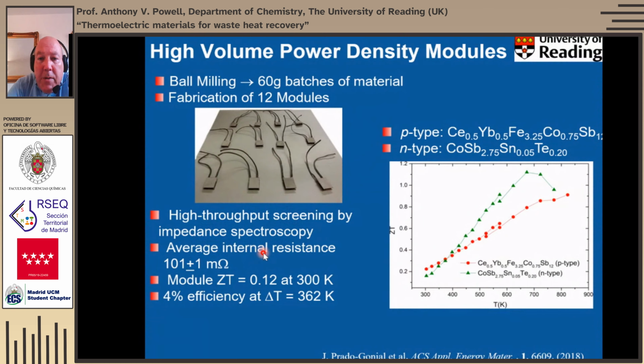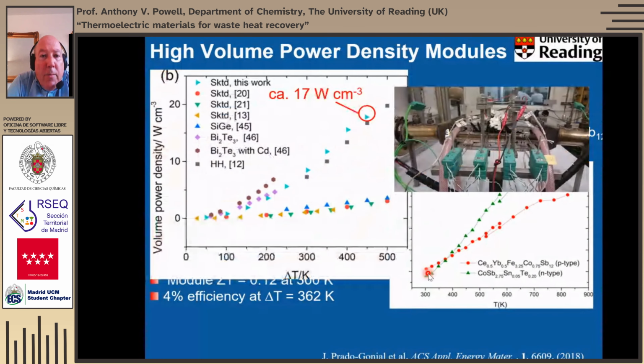Now, despite the fact we get materials with high ZTs, so here are the materials that went into these high volume power density modules, at ZTs of about 1.1 to 1.2 maximum, the module ZT at 300 Kelvin, so down here, is only about 0.12, whereas the materials themselves are maybe just above 0.2. So we lose a lot of performance in fabricating the module due to contact issues and so on. But nonetheless, we do get something that's about 4% efficient at a delta T of 362 Kelvin. It produces about 17 watts per cubic centimeter.